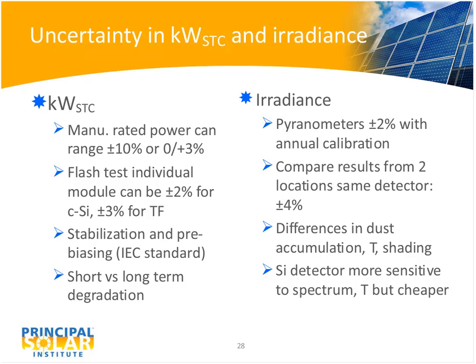Now, if you look at irradiance, you're monitoring the outdoor test illumination at your installation site. The best you can do with pyranometers is about plus or minus 2% with annual calibration. And if you're comparing two locations, even if it's the same brand of detector in two different locations, you're now looking at a plus or minus 4% variation in the annual irradiance at those two locations. And then different detectors can accumulate dust differently than the modules that you're measuring, or they have different temperature sensitivity than the module you're testing, or maybe they're shaded differently. So you can now get differences between the detector and the actual illumination on the module itself. So that adds additional uncertainty in the measurement.